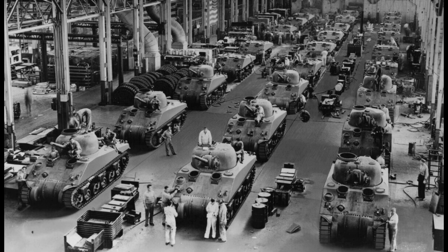In practice, Welder immediately saw a serious problem that concerned him. That remaining quarter-inch of unfused metal at the root of the joint created what metallurgists call a stress concentrator, a weak point where the two plates weren't truly unified into one piece. On a ship moving through water, that joint would hold fine because the forces were distributed evenly and mostly tensile in nature. But a tank took impacts, high-velocity impacts from projectiles specifically designed to find and exploit weak points in